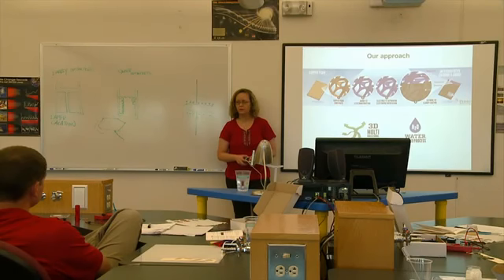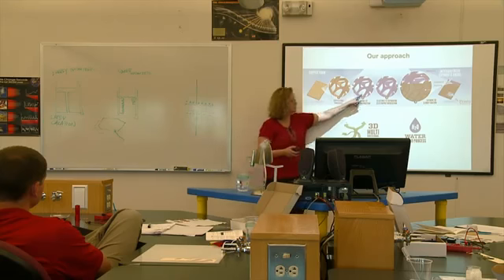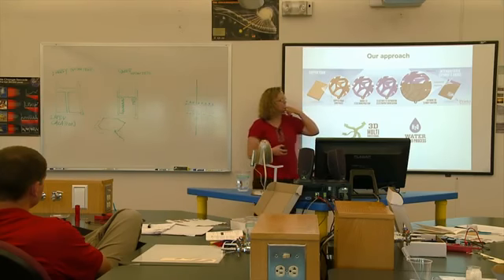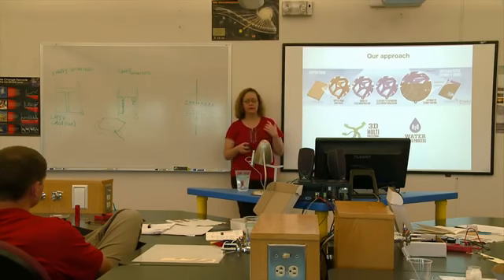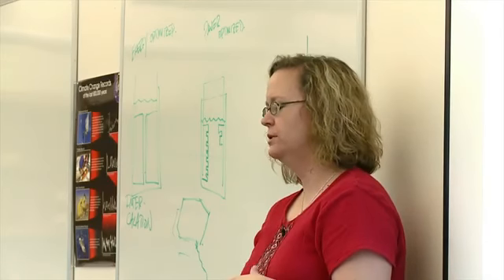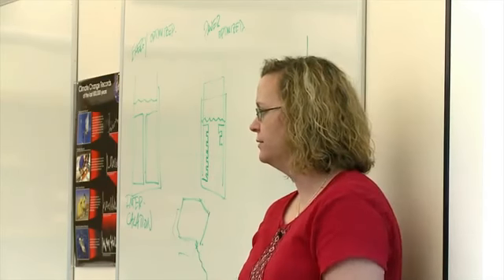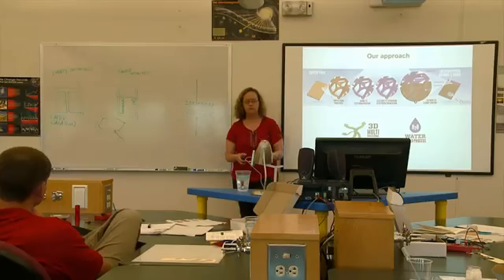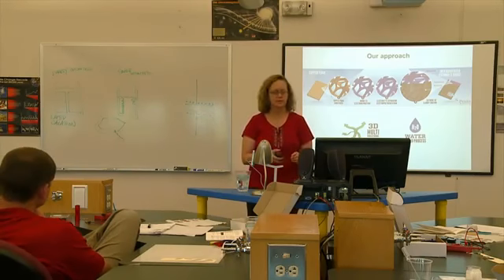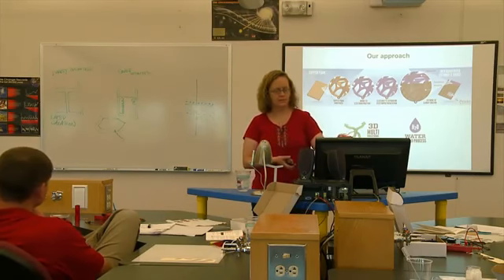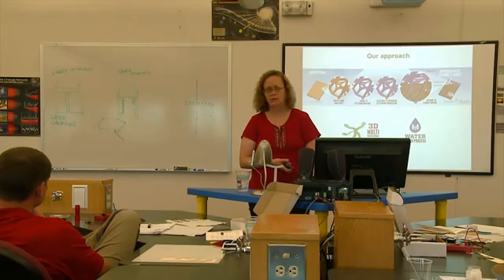A normal lithium ion battery runs at about 3.6 volts. We've made our polymer stable up to about 8 volts because we figure there might be hot spots, especially where you see all these little curves. And we have to have a way to plate it so that it really does cover every piece of the battery, otherwise you get a short. So that's what I'm going to spend the rest of the time talking about today, the anode deposition and the polymer deposition. And I wanted to show you actual structures and data.